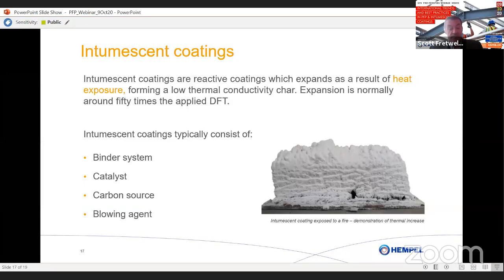So what is an intumescent coating? This is a reactive coating which resembles, on a normal day, a decorative system. And once applied, will lie dormant on the steelwork. However, in the event of a fire or exposure to heat, the coating will expand to form a low thermal conductivity char, which slows down the temperature rise of the steel to protect the steelwork for a given period of time.